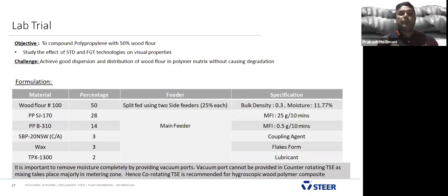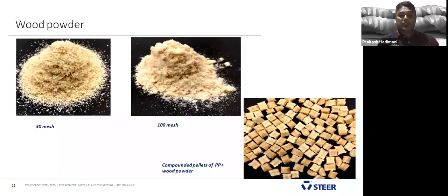Okay. And also the bulk density of this is 0.3 or less. And the moisture content we observed is almost 12%. We didn't pre-dry. Our twin screw extruder, the FGT, is capable of removing moisture. These are the two powders we have used for the lab study, 30 mesh and 100 mesh. The 30 mesh was coarse and flaky in nature, and the 100 mesh was a fine powder.